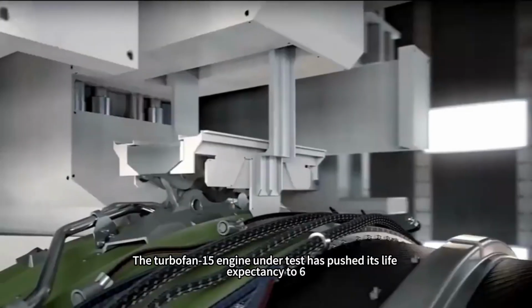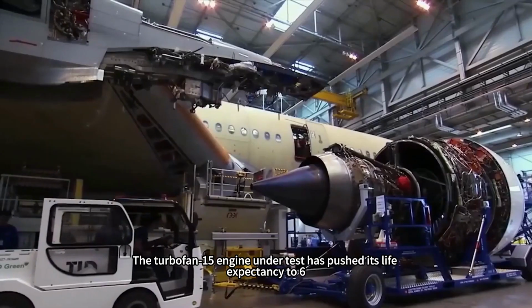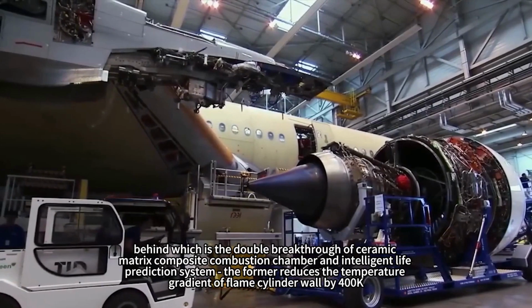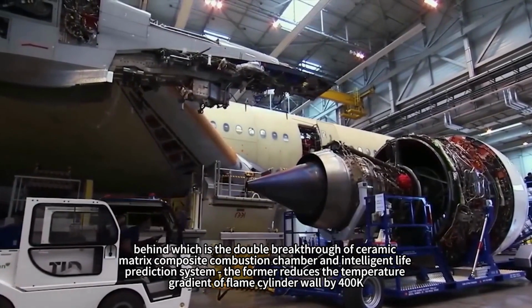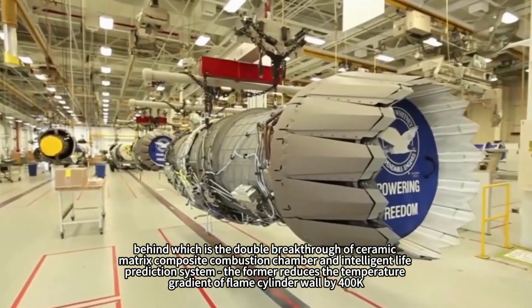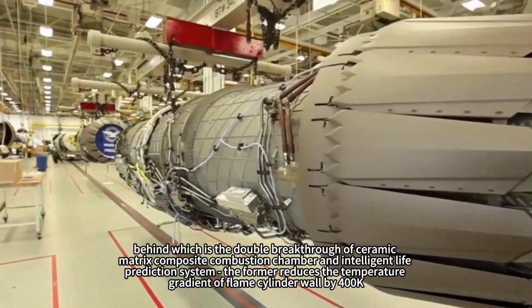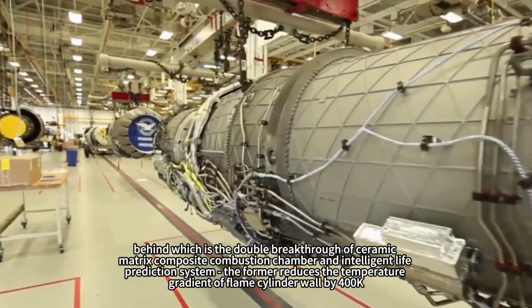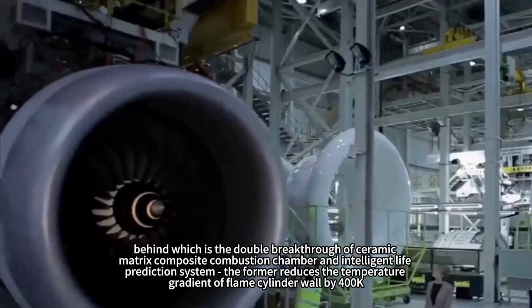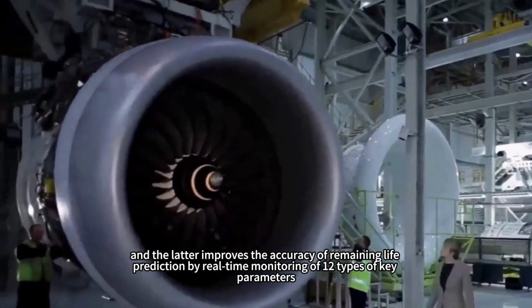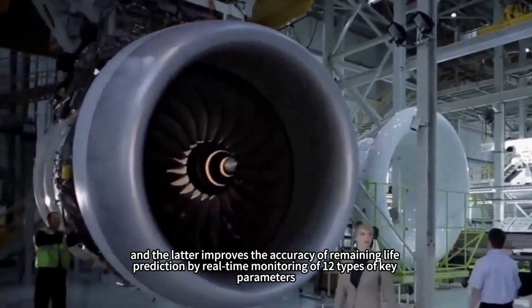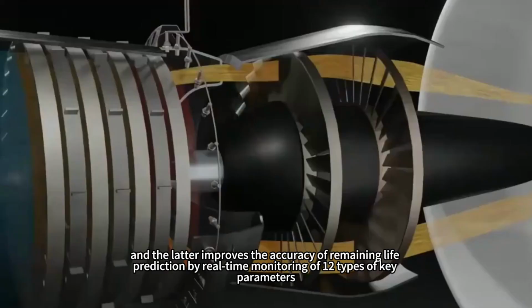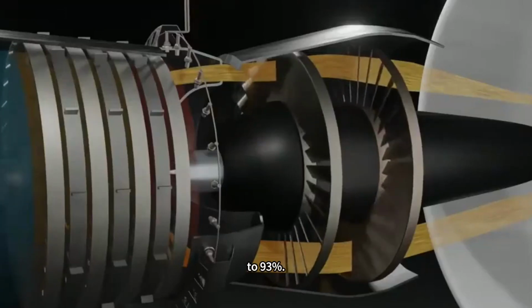The turbofan 15 engine under test has pushed its life expectancy to 6,000 hours, behind which is the double breakthrough of ceramic matrix composite combustion chamber and intelligent life prediction system. The former reduces the temperature gradient of the flame cylinder wall by 400K, and the latter improves the accuracy of remaining life prediction by real-time monitoring of 12 types of key parameters, reaching up to 93%.